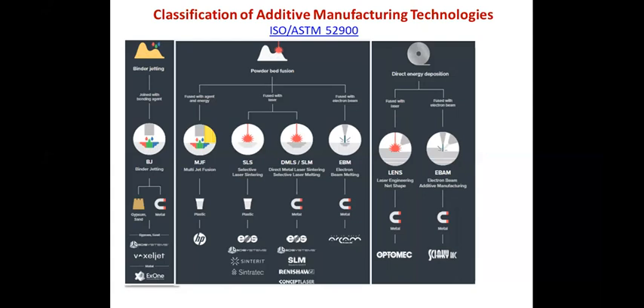And direct energy deposition is another classification, where the metal powder and the energy source are sent through a nozzle. In the previous powder bed fusion, the powder substrate is deposited on the build chamber and the laser scans it. Whereas here, in direct energy deposition, the powder as well as the energy source, whether a laser or an electron beam, meet at a particular distance, just below the nozzle tip, where the metal powder gets melted by the energy source and is deposited.